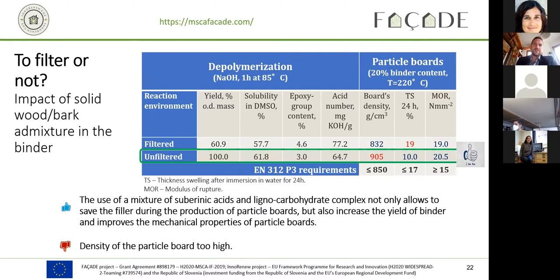When the depolymerization environment was selected, we tested the impact of solid wood bark admixture in the binder. We tested filtered and unfiltered binder suspension in water. And we concluded that the use of a mixture of suberinic acids and the lignocarbohydrate complex not only allows to save the filler during the production of particle boards, but also increases the yield of the binder and improves the mechanical properties of particle boards. Still, as you can see, the density of the particle board was still too high.